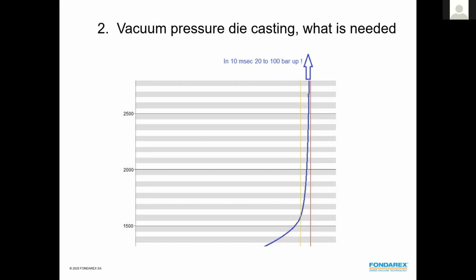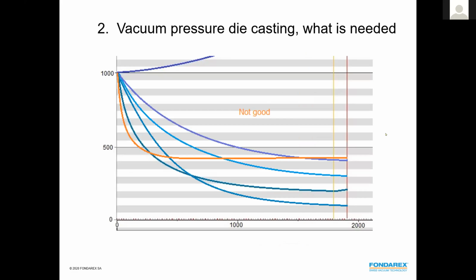And there is the big problem: the last 10 milliseconds. In the last 10 milliseconds, a lot of things happen which we are not able to control if we do not work with vacuum. This is a very positive point of vacuum, because we take out the air before the metal is at the gate. And once the metal is at the gate, we remain with a rather low pressure, or let's say almost no air, somewhere between 500 and maybe 20 millibar. 500 would be here, and 20 down here.